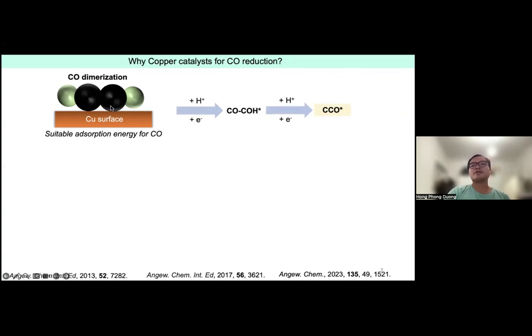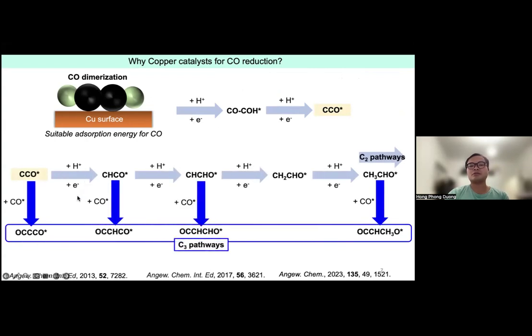Okay, you see by CO dimerization, it can form different intermediates here, and those intermediates are very important to go to higher chain products. For example, you can have different C3 intermediates as shown here, and those C3 intermediates were in fact modelled by DFT calculation, and also there are several reports recently trying to use spectroscopy to detect those intermediates to clarify.